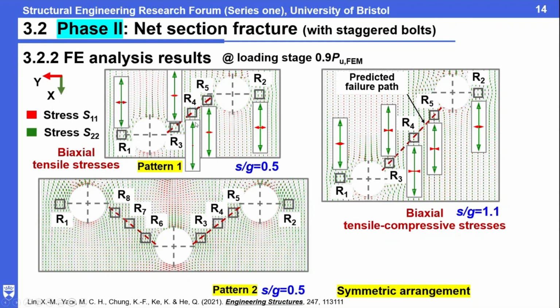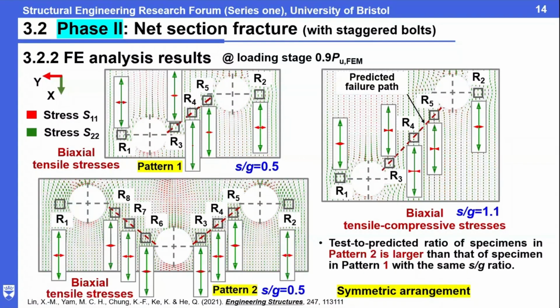When it's lower than 1, the stress state is biaxial, tension and tension. However, if S is larger, like this, it is no longer biaxial tensile stress; it becomes tension and compression. When you analyze it by the Mohr circle, you will find that if one is tension and one is compression, it will make the resistance lower. It will not be the reinforcement and will be a little bit weaker. And if we use a double pattern, similar to a symmetric one, it will enhance the reinforcement. So, based on the validated numerical model, we found the reason why the symmetric pattern has a larger ratio compared with the non-symmetric way.